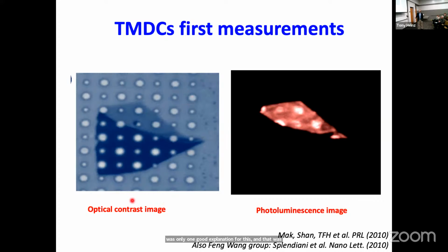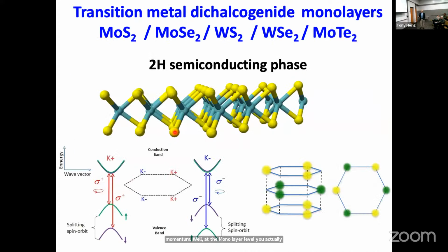It was known that the bulk materials have an indirect gap, which means light emission is inefficient because a photon has to be involved to conserve momentum. Well, at the monolayer level, you actually transition to a direct gap material with efficient light emission. So from that point of view, it actually looks quite a bit like what happens in graphene, where these Dirac cones that you've probably all heard about reside at the corner of the Brillouin zone. So you have a kind of a similar configuration here, but you have a direct gap, and that's something distinctive to the monolayer. The other thing that's different is you don't have this linear dispersion.